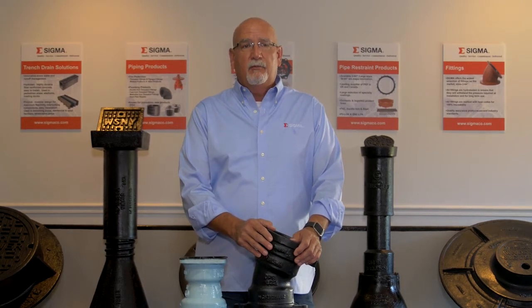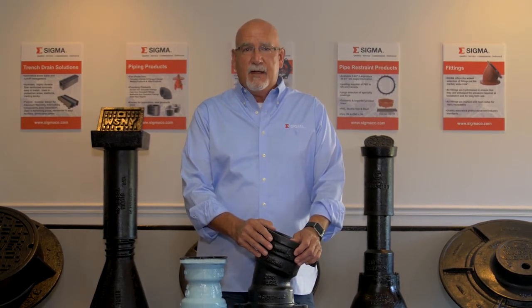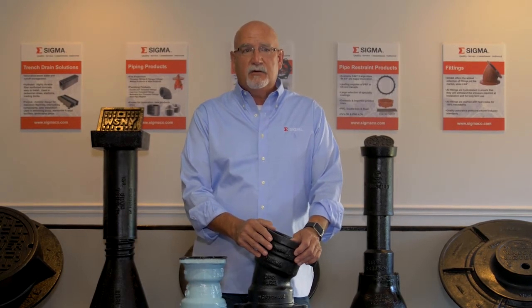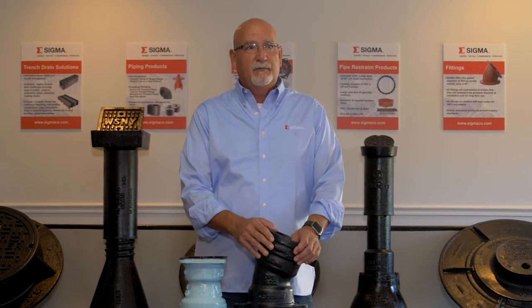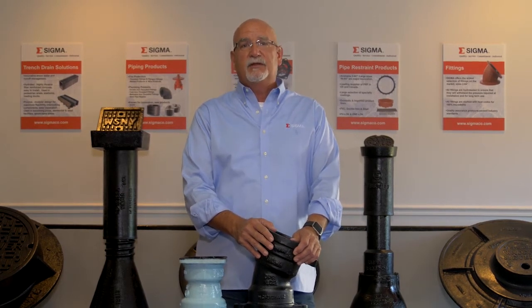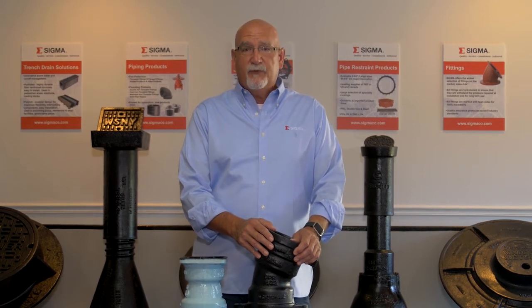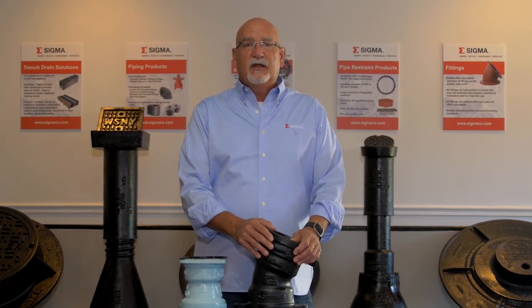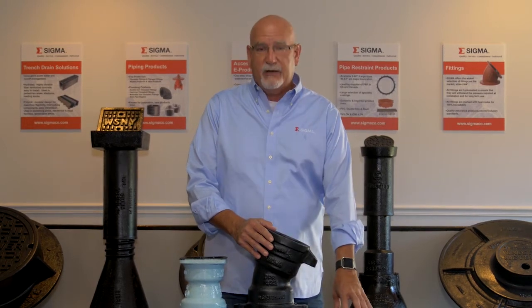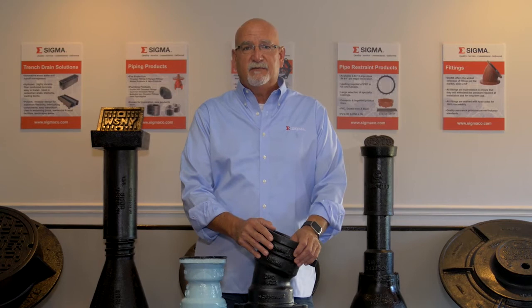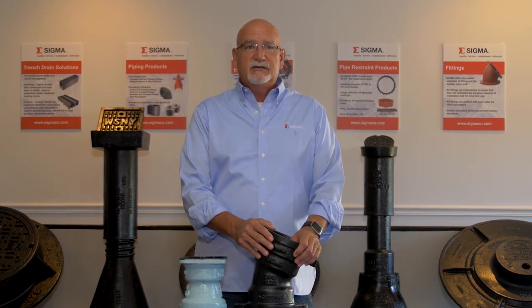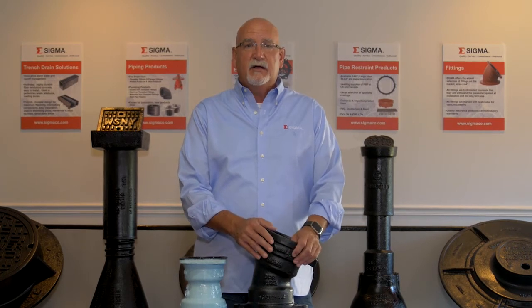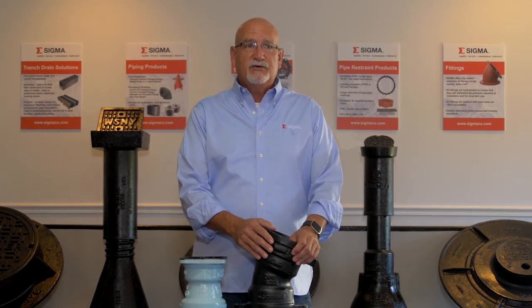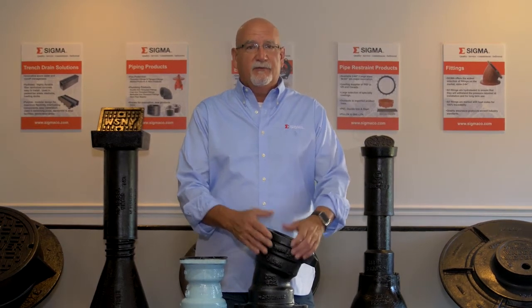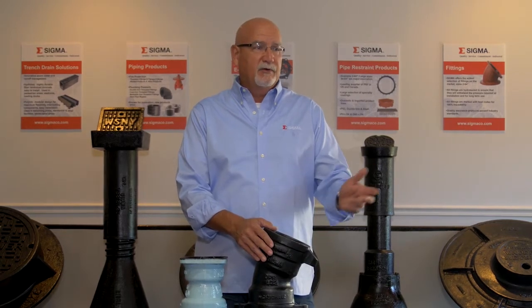There's also several brands of primer that would be considered barrier primers. They are two-part epoxy. The most common, and the one that most all of our folks are familiar with, is a Tnemec product, 140-1211. The 1211 is actually the color code. It's this same red primer color, but it's a two-part epoxy that's a very, very good barrier coating. It's designed to create a barrier, plus it's also designed as a primer so that a top coat can be applied in a particular application where someone is concerned about having different colors on top of their pipeline to identify certain processes.